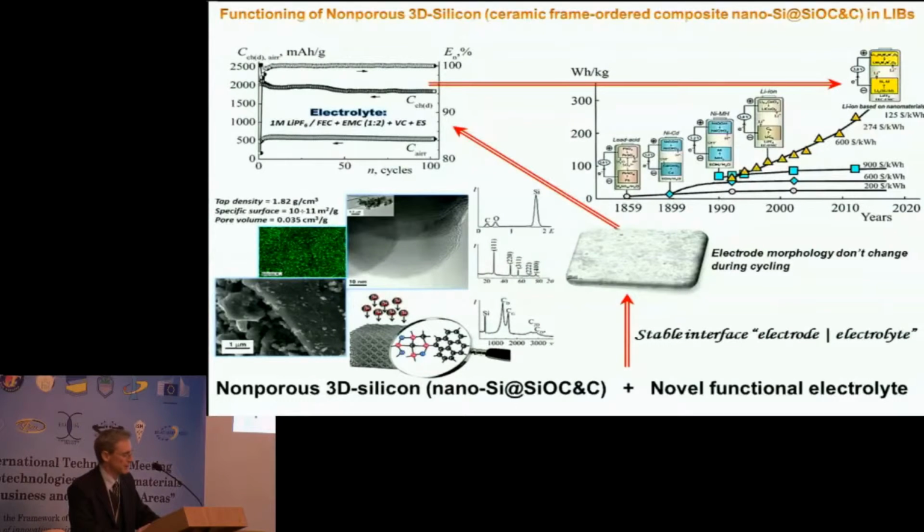Such a strategy does not seem promising for practical use because of the low loading capacity of the suggested electrodes and the low coulombic efficiencies of the cycles, due to renewing contact of the active surface of the swelling lithium-silicon alloy with electrolyte. For the first time, as a key characteristic parameter for rapid assessment of the usefulness of developed electrode materials and electrolytes for lithium-ion batteries, we propose to use the value of the irreversible capacity accumulated in N cycles,